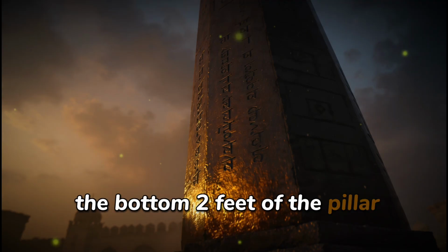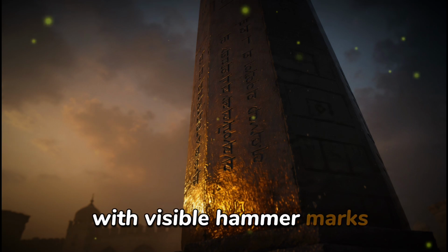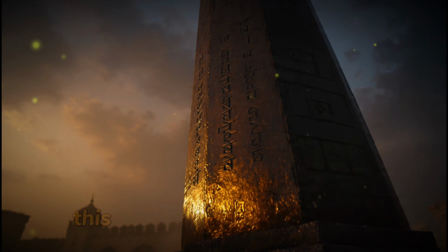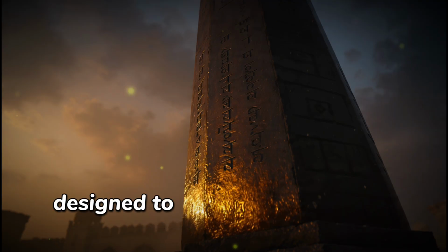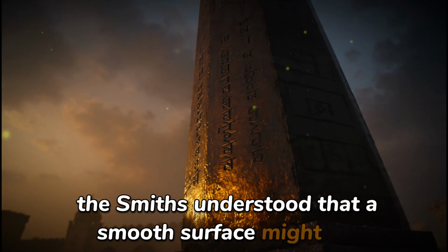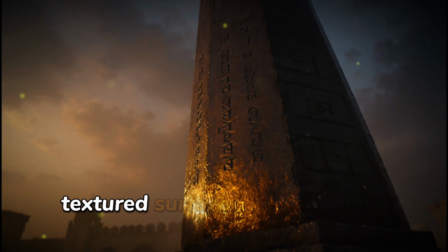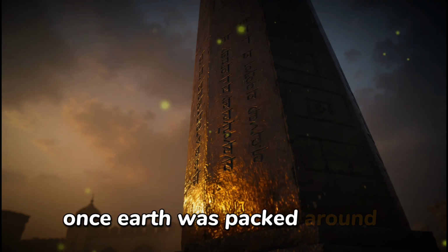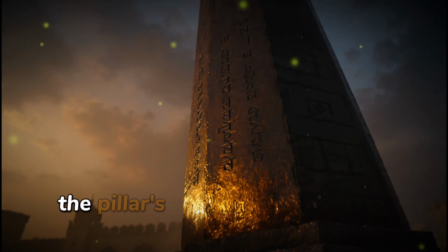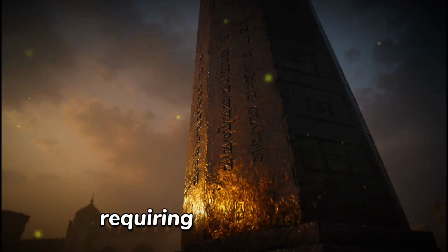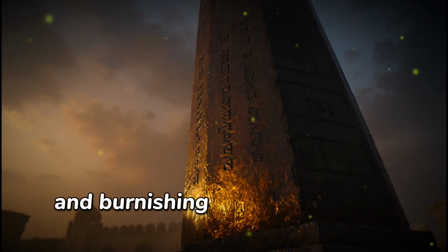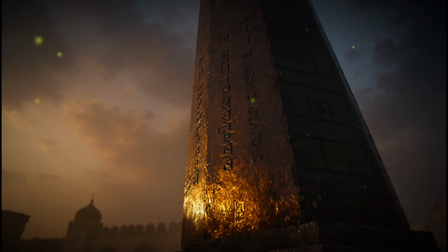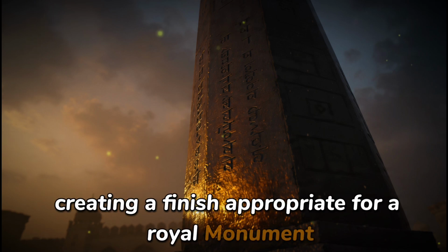The bottom 2 feet of the pillar show rough texture with visible hammer marks. This wasn't poor craftsmanship. This roughness was intentional, designed to help the pillar grip the ground when buried. The smiths understood that a smooth surface might slip or rotate, but a rough textured surface would lock into place once earth was packed around it. Above ground level, the pillar's surface is smooth and polished, requiring additional work after the forge welding was complete. The smiths used chisels and burnishing tools to create this refined surface, removing the rough scale and hammer marks, creating a finish appropriate for a royal monument.